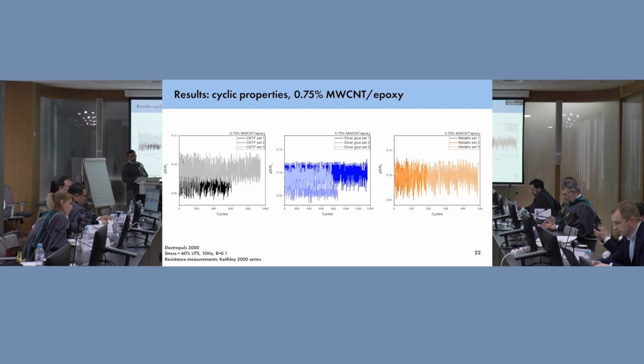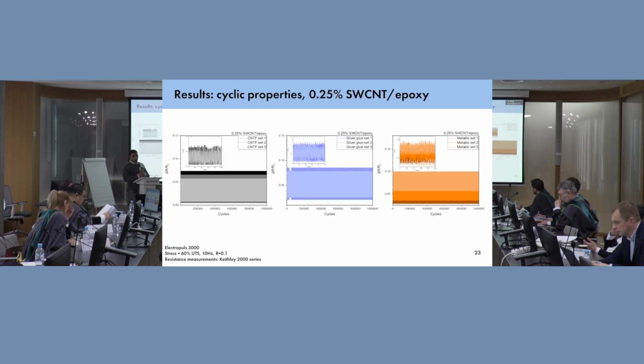And our surface applied ones are performing the best, of course. But the thing that we wanted to see only was, is our response there? Can we read it with these type of electrodes that we propose? And how do they perform against metallic, which was the most important? For our very conductive composites, we see, again, response is pretty much the same.